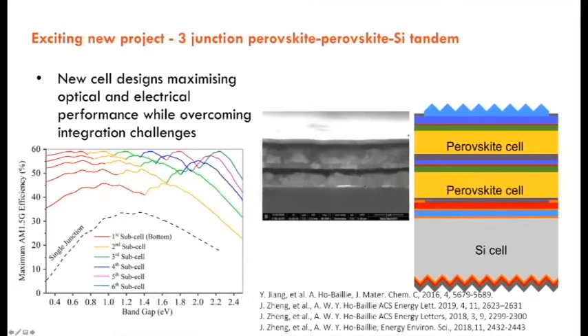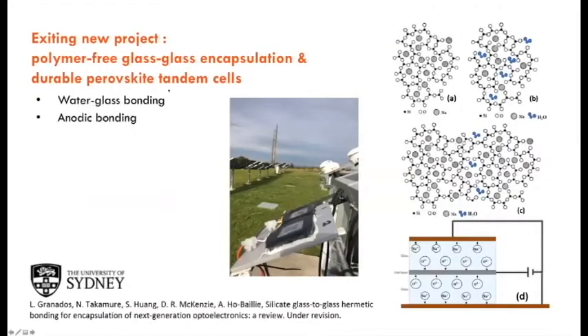We're also awarded another project of looking at stabilizing perovskite cells and perovskite tandem in this case. Because perovskite is easy to make, it can degrade easily if we're not careful. So I will talk about the polymer glass encapsulation that we have developed, which managed to stabilize the cells. But in this project, we're looking at the polymer-free glass encapsulation by bonding 2 pieces of glass together at low temperature, because perovskite doesn't like very high temperature. So that's one challenge. So there's new glass technology and also new knowledge about how to stabilize cells.